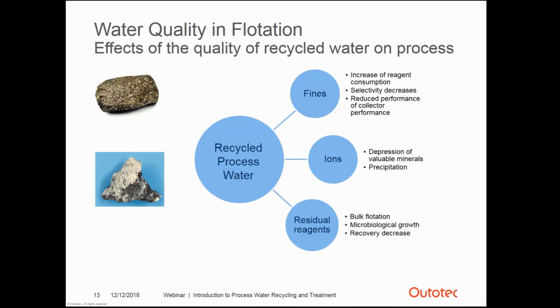If the pH is favorable for precipitation, some ions may precipitate and disturb the flotation process. For example, gypsum formation between calcium and sulfate ions. Gypsum will precipitate on finely ground mineral, and this way block the site where the collector can attach.